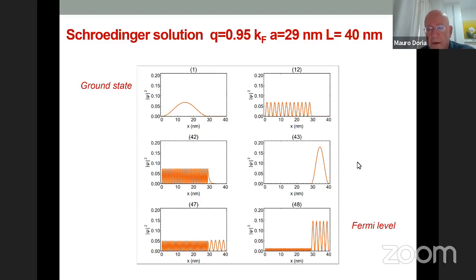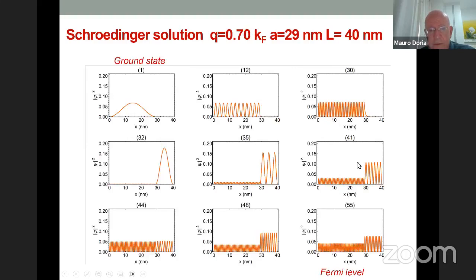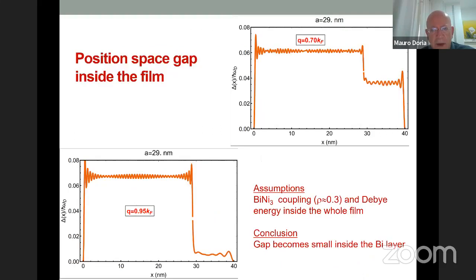So this is what we observe. That's another barrier, and we see the same effect. Electrons in the initial fundamental levels are just on the bismuth nickel 3 side, but at the end, near the Fermi energy, they are in both. And that's why the bismuth becomes important in the superconducting state, because electrons can visit near the barrier.